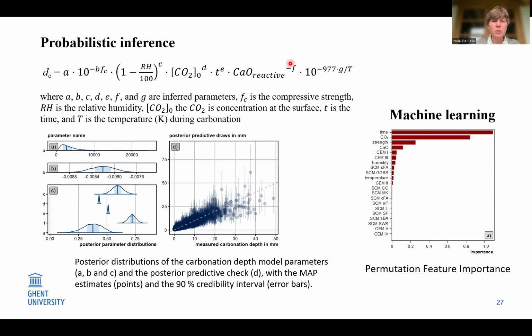Therefore, the strength was also included in a probabilistic model, and you can see here all the different parameters that were included, and the different coefficients here were then calculated with this probabilistic model. So for instance, it was seen that the reactive calcium oxide needs an exponent F, and this exponent F is considerably less than 1, as you can notice here.